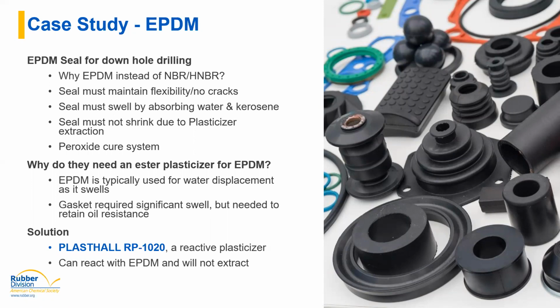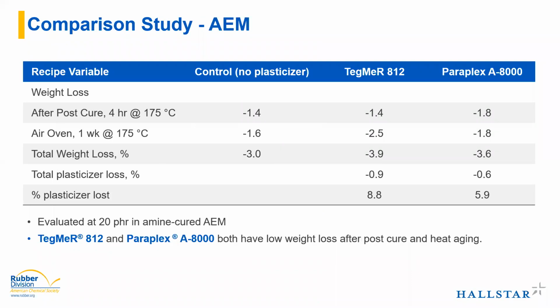And so it was not extracting out, it was not migrating because of incompatibility, because everything was bonded together, and it was able to give them the needed swelling from the water, but still have resistance to the oil in the end.